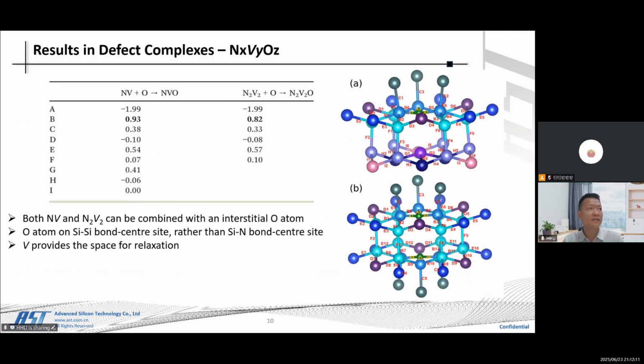For the NVO complex, both NV and N2V2 can be combined with an additional interstitial oxygen atom. The oxygen atom sits on the silicon-silicon bond center site rather than on the silicon-nitrogen bond center site. The vacancy provides the space for relaxation, as shown in figures A and B.